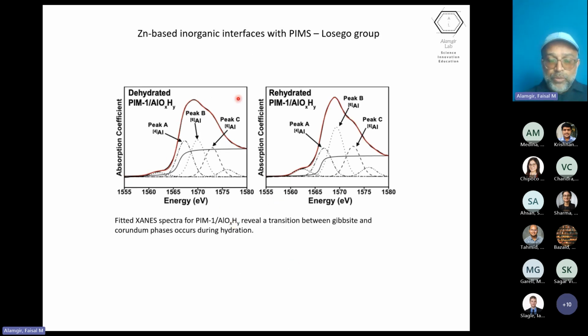But here's another work that we are collaborating on. It's the same type of reaction, but for aluminum-based oxyhydroxide structures that are growing on PIMs. But aluminum happens to be at an energy range, if you want to interrogate aluminum, that we cannot access with our current instrument. And because we can't access it with our current instrument, we had to go to synchrotron, and this is synchrotron-based data that is showing a transition between Gibbsite and corundum phases of this alumina.